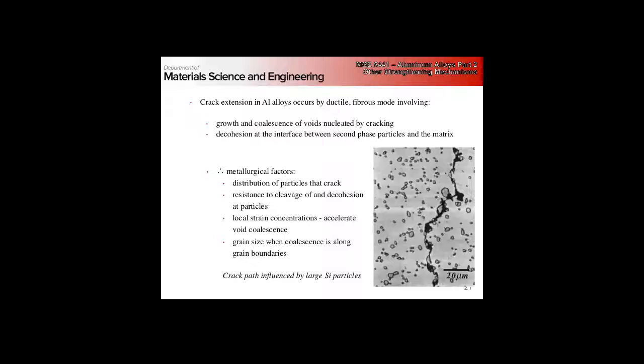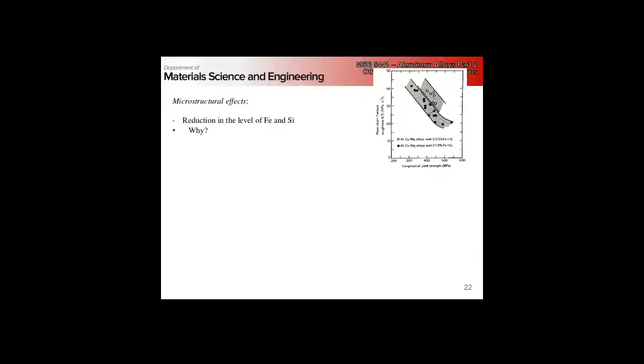Right? So particles can cleave depending on the surface energy. We can have decohesion. Right? This gives us very large local strain concentrations, which can then accelerate the void coalescence. Right? And depending on the alloy, we can also zip along grain boundaries, right? Especially in alloys that are subject to stress corrosion cracking, like aluminum mag, right? If we have a large amount of grain boundary, a brittle grain boundary beta, especially in a hydrogen environment, it becomes even more brittle, right? Then we have a crack that just can zip along the intermetallic that's on the grain boundary, right? Without much resistance. Okay, so the first thing we want to do is try and reduce the level of iron and silicon.